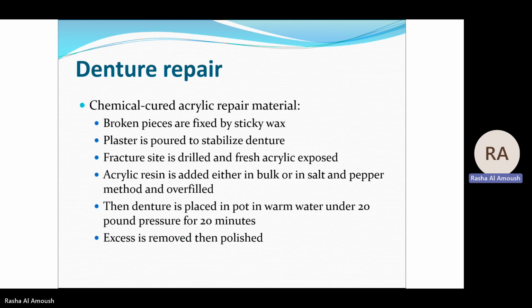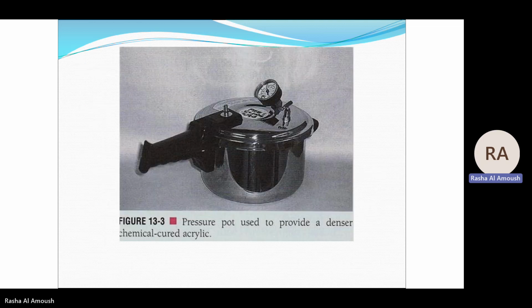Also, we can use acrylic resins for denture repair. We can use chemical cured acrylic materials. If we have broken pieces, you can fix them together with sticky wax. The plaster is poured to stabilize the denture, and the fracture site is usually drilled and freshly mixed acrylic is exposed. Then we mix acrylic resin and add it over the fractured part, the excess is removed, and then the denture is polished.